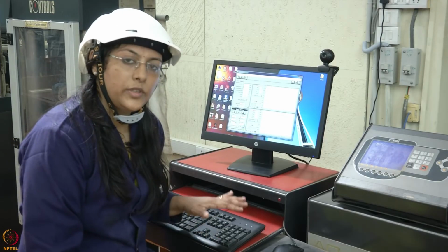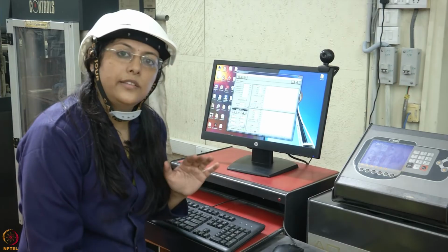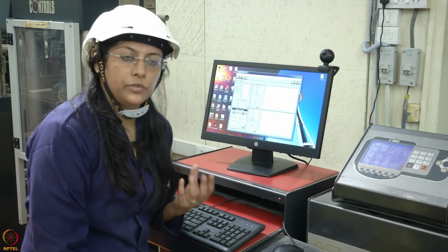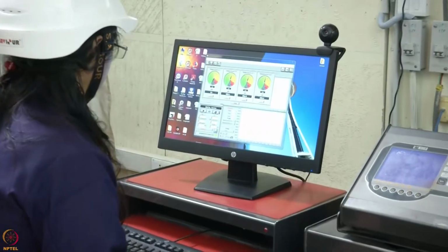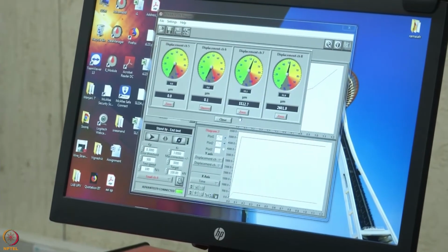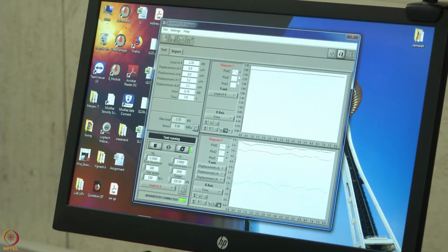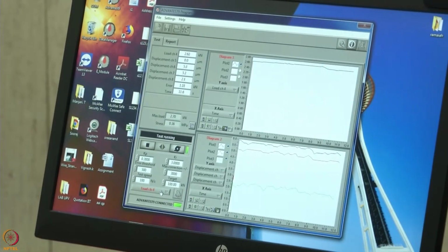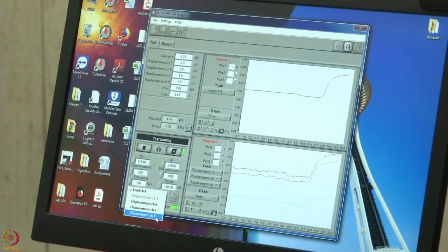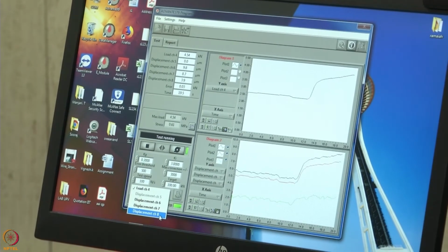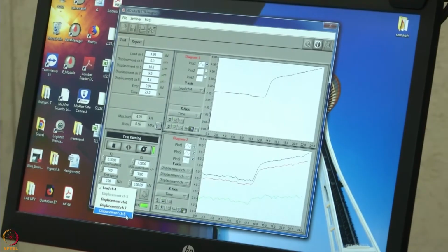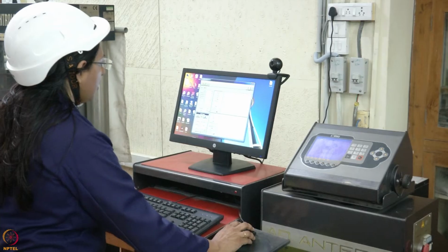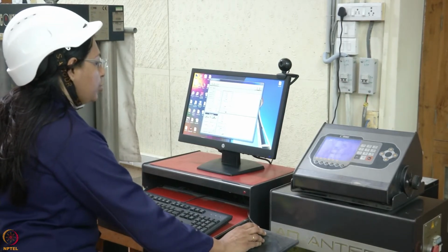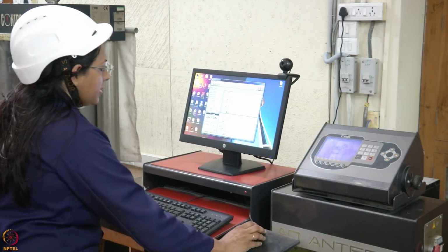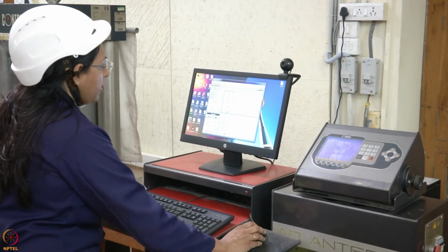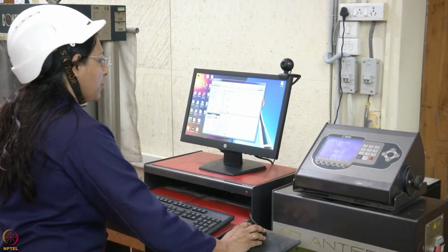Initially we start the test with load control till around 40% of the peak load is reached, and then we shift to CMOD, or crack mouth opening displacement control. Now let's move on to the test. Now the test is running. The peak load is achieved in 2 to 3 minutes, and the complete duration of the test, that is for a CMOD of around 4 mm, takes around 45 minutes for steel fiber reinforced concrete.